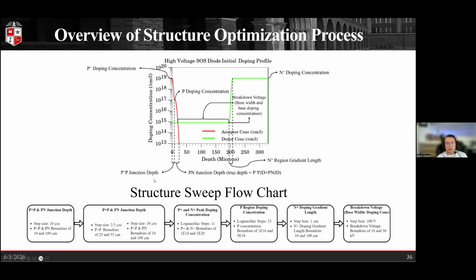And with that, we ended up doing a logical incremental process, where first we swept the P plus P and PN junction depths. The P plus P depth is the depth from our anode contact, basically, to that P plus P junction. And the PN junction depth is, of course, where our P material meets our N material. You can see we did a step size of 10 microns, and we had boundary conditions of 100 microns. So we swept all the way in between that.